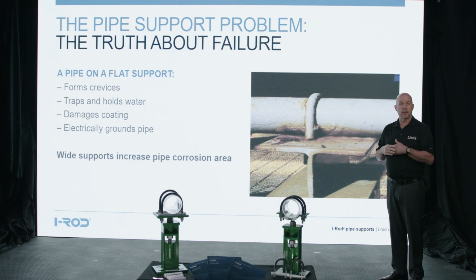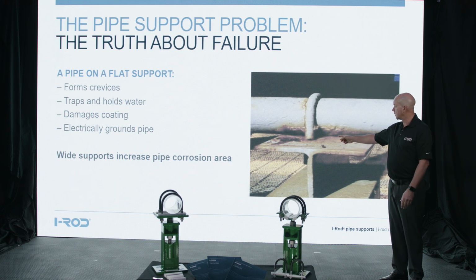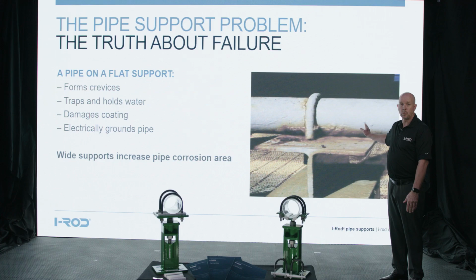Here's the truth about what happens. The pipe sitting on a flat surface creates a crevice. The crevice traps and holds water. That damages the coating. And then you have the pipe sitting directly on bare steel, which electrically grounds the pipe. And a wide support creates a bigger area of concern or a bigger area of problem. As you can see in this image, a nice wide beam, and the corrosion is happening all along the surface of the pipe that is in contact with the support, but you don't see the same thing where it's not in contact with the support.